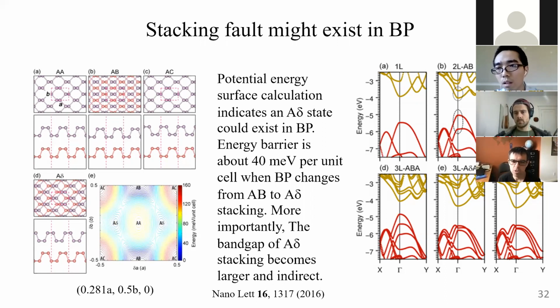One way would be to look at the photoluminescence, and usually indirect systems don't have much photoluminescence. So were you able to observe photoluminescence of that? That's a good question. We have tried to measure the photoluminescence of black phosphorus from liquid exfoliation, but we didn't observe any signal. But for the mechanically exfoliated BP, we could easily observe the photoluminescence.